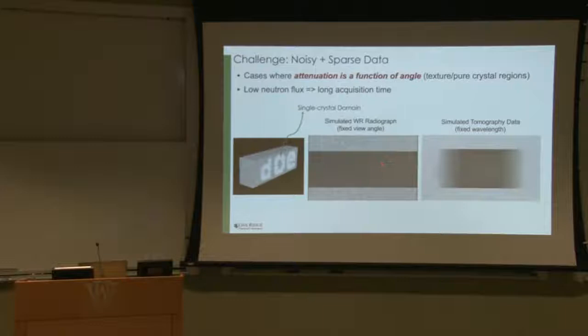So what you're seeing is a 3D sample. This has been simulated using realistic noise levels, and you can see it's pretty noisy. And similarly, if I take the same object and now do a CT of it, yeah, so what you're seeing is a CT scan of this part, a simulated scan. So this is the measurements. So at some angles, you'll see it lights up because the crystals were just oriented right, and you see a big scatter away. And so the transmission sees a big drop. So the question is, how do we go from here to get the 3D object back? So that's what this part is going to be about.